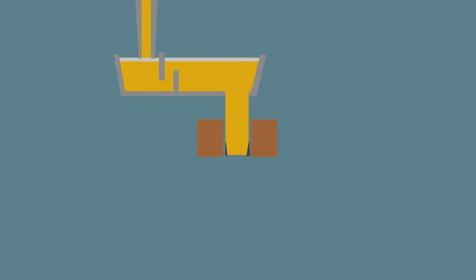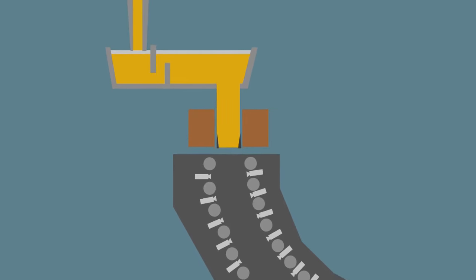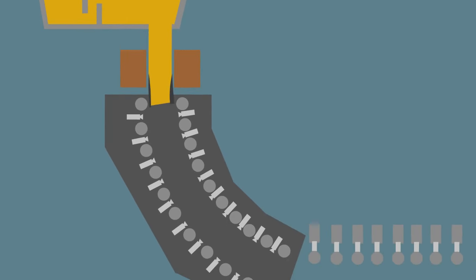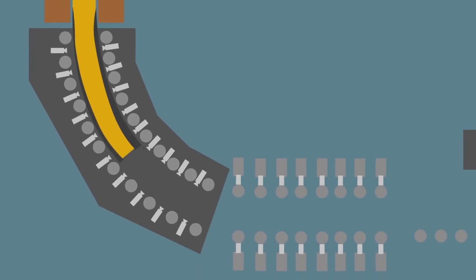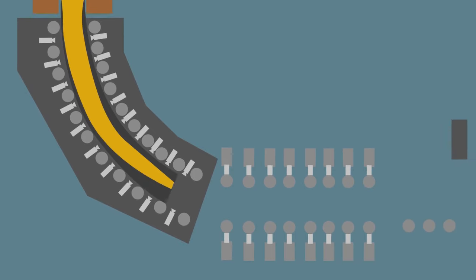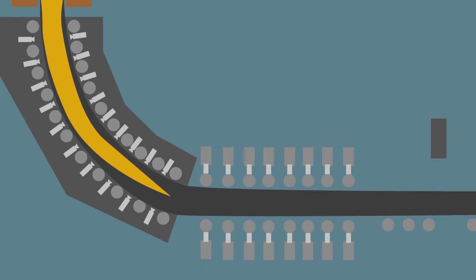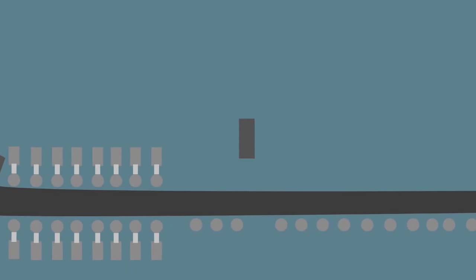The cooling is controlled and only the outer skin of the steel is solidified. The molds are oscillated to ensure that the solidifying shell does not stick and break. Flux is also added to aid lubrication. The steel shell grows as it is drawn down through a curved arrangement of support rolls and water sprays. It then emerges horizontally as solid steel strands and is cut to length with automatic gas burners.